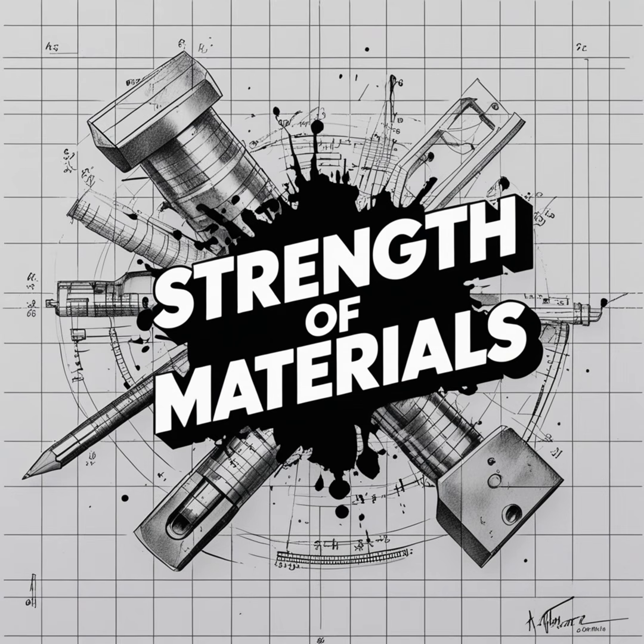Case 2, low stress first, high stress second. In case 2, you apply the gentle low-stress cycle first. It isn't high enough to cause any microcracks. But what it does do is manipulate the internal lattice. It causes dislocations to move and tangle up around each other. We call this strain hardening. Strain hardened. Yes. The surface of the metal actually becomes physically harder and stronger.